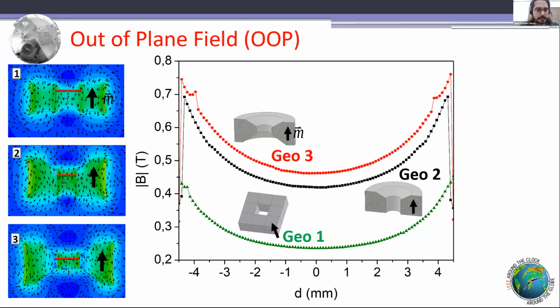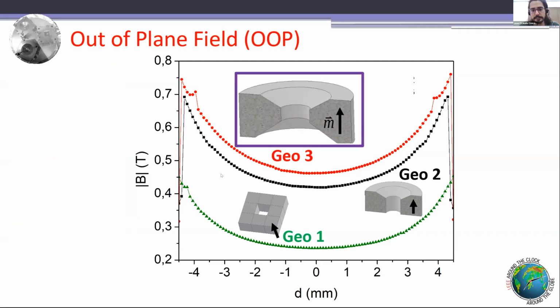And for the out-of-plane field, we designed three different geometries. One with cubic magnets similar to the previous one, 1 by 1 centimeter cubes, with the magnetic fields aligned perpendicular, and the others with a donut shape. One is a completely round donut shape, and the other has optimizations, so you can reach higher magnetic intensity only in our region of interest. Doing the simulation, we chose the third geometry, the best one, which can keep up with the same magnetic field as the in-plane array.